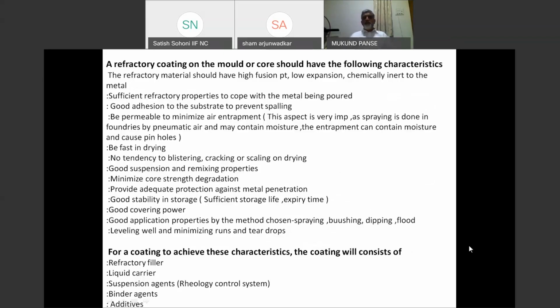A refractory coating should, the basic refractory, have a high fusion point. We are trying to give a coating of refractory fines on the mold surface, but the dry refractory cannot be coated, so it has to be carried through some liquid so it can be sprayed or coated properly. Normally, the carriers are either water or alcohol, spirit base.